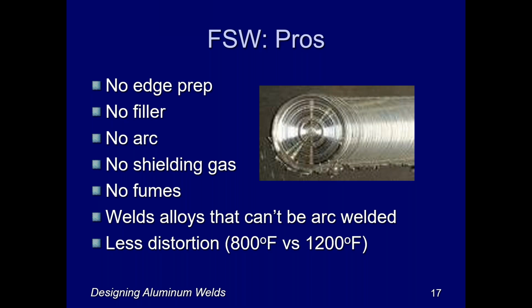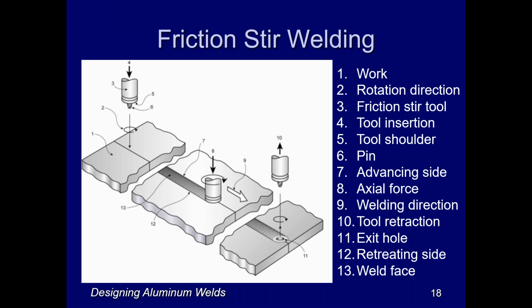And you do this all at a lower temperature than the melting temperature. In other words, instead of 1200 degrees, which is an average melting temperature for most aluminum alloys, you do it at 800 degrees, and therefore you have less distortion and less heat effect on the base metal. So the process looks something like this.